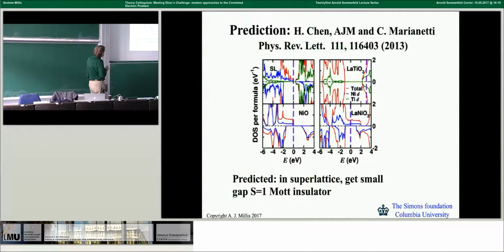The main thing to focus on is this is lanthanum titanate, which is a Mott insulator with this gap. This is lanthanum nickelate. You can see the Fermi level here. At 0, it's a metal. There are states overlapping the Fermi level. This is Hanghui's superlattice with an energy gap at the Fermi surface and states near the chemical potential very similar to those in nickel oxide. So the prediction is that in the superlattice you get a small gap spin 1 Mott insulator out of these two components, a spin half Mott insulator and a metal.